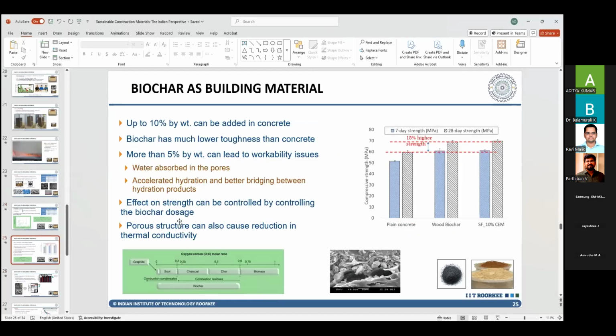So what is the research around this? Well, if you're using it in normal concrete, you can go as high as 10% by weight of cement. So suppose you are using a normal concrete with about 350 kg per cubic meter of cement content, you can add 35 kg of biochar to it. And that 35 kg, assuming 70% carbon content, would be approximately 25 kg of pure carbon that you're storing inside the concrete.